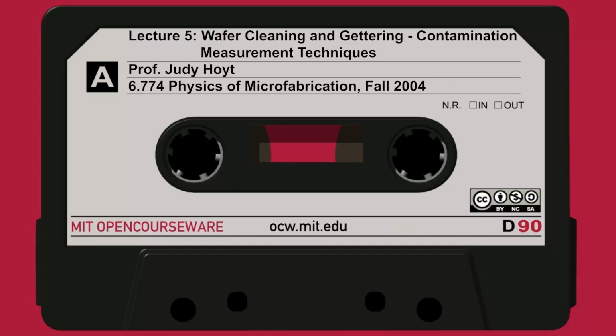So let's go on to slide 31, rather, and talk about these different charges. First, there are basically 4 types of charges associated with the insulator itself or the semiconductor-insulator interface. The first one you may have heard of, called QF, or Q sub F. It's the fixed oxide charge, represented here by these little positive plus signs. It's a sheet of positive charge, and it's supposed to be within about 2 nanometers of the interface.